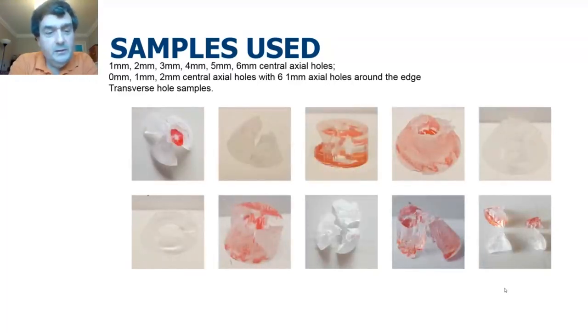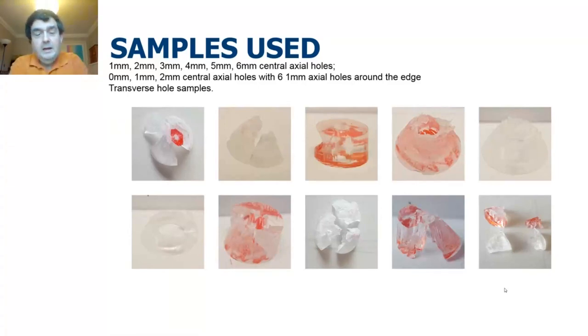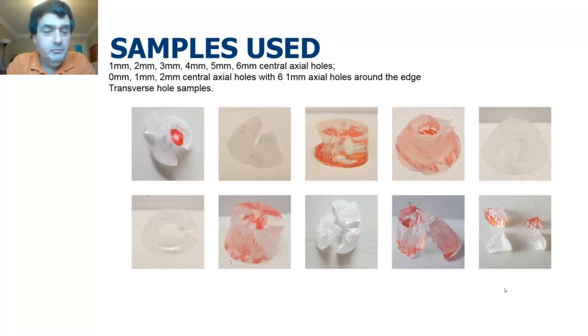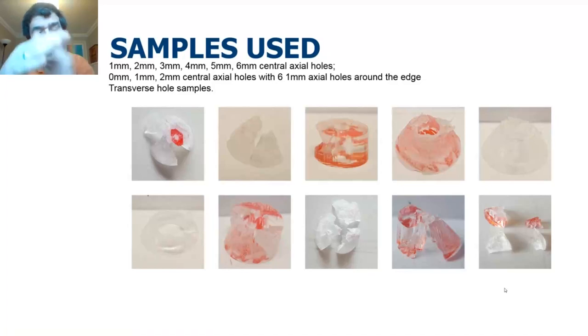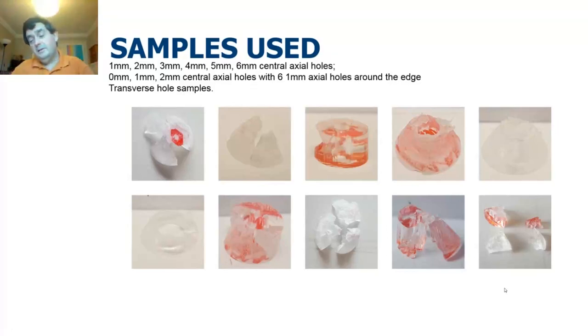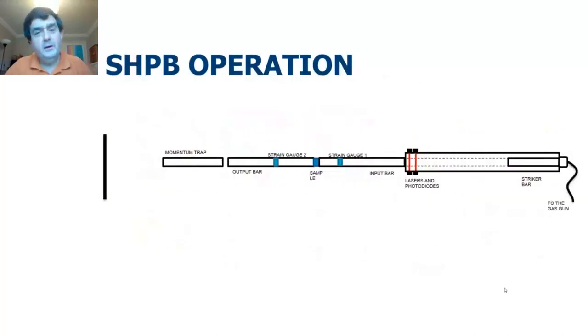Afterwards, this is the kind of damage we find — a lot of wedge formation. You can see some wedges that have been popped out of the sample under different loadings. For the multi-hole system, the holes tend to capture cracks and you get more diverse cracking. In the bottom row you see a wedge system, then a system with a central hole where the wedge is still obvious, then for the transverse hole there's no more cone formation — things simply fracture.